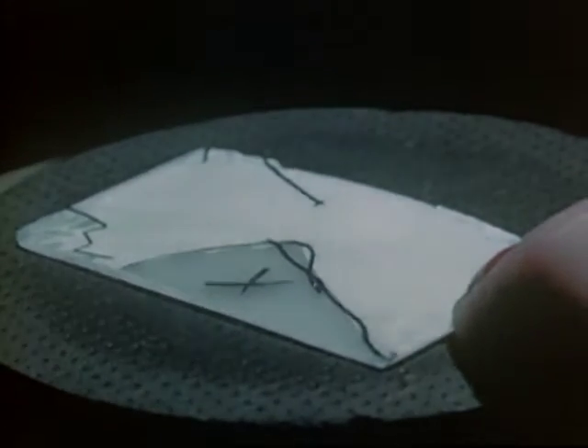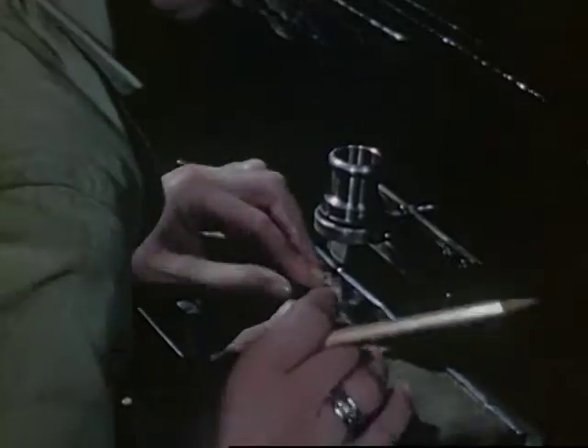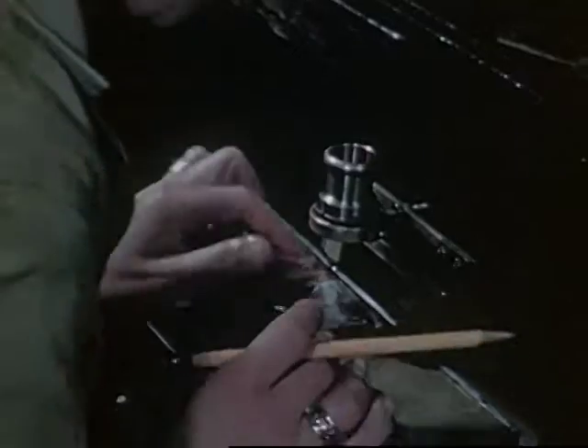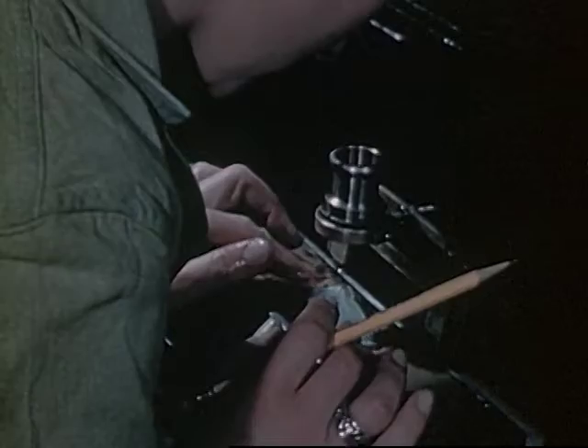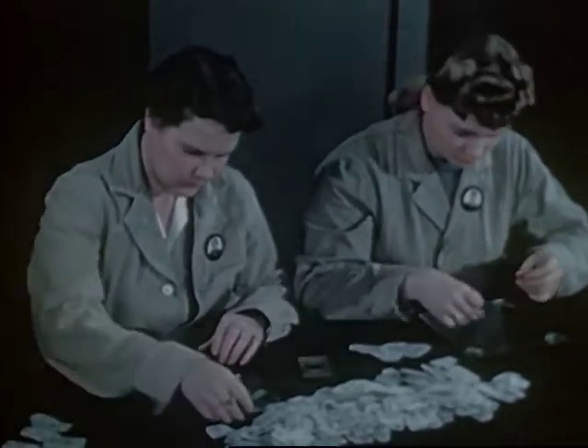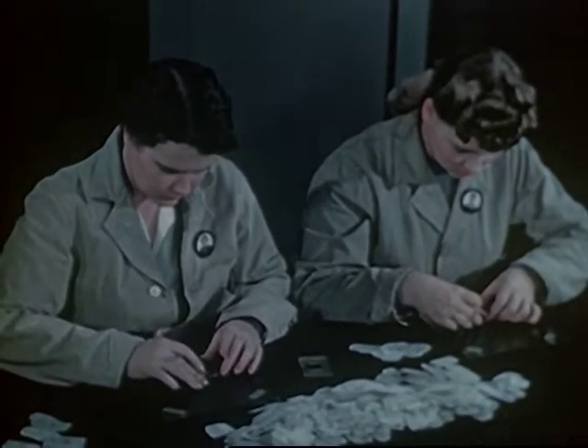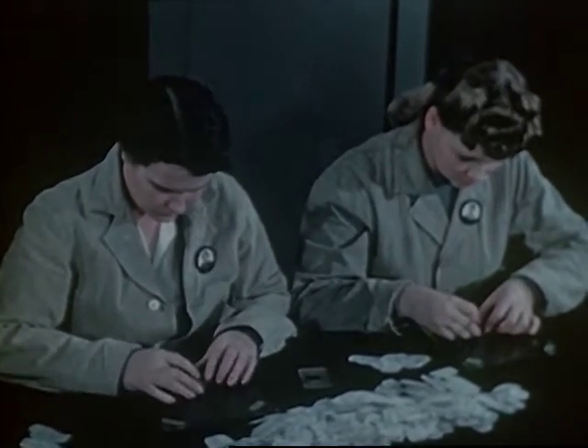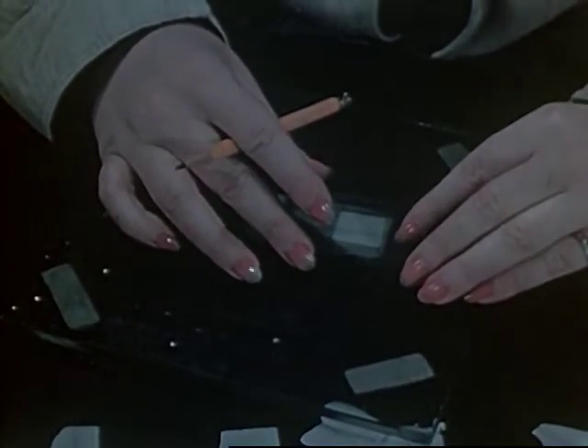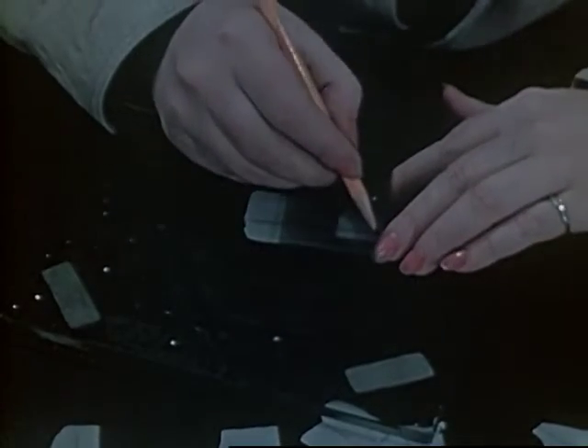The wafers are again examined, this time in the polariscope, in order that when square plates are cut, their edges may be lined up with the electric axis of the quartz. A line indicating this direction is drawn upon them. In marking out the wafers, they are squared up with this line. The workers space their lines carefully so as to get as many plates as possible from the wafer.